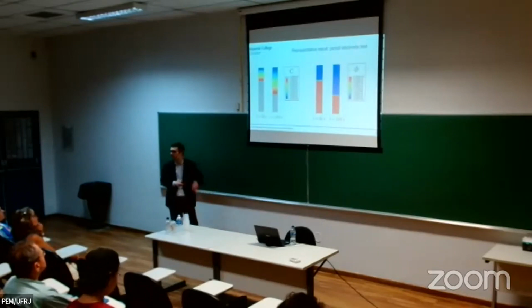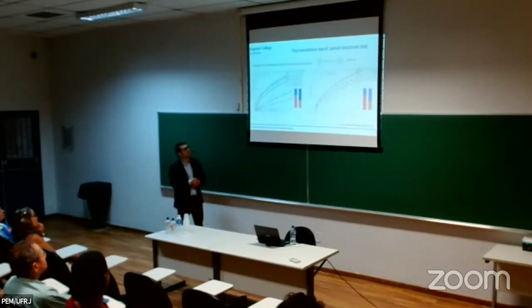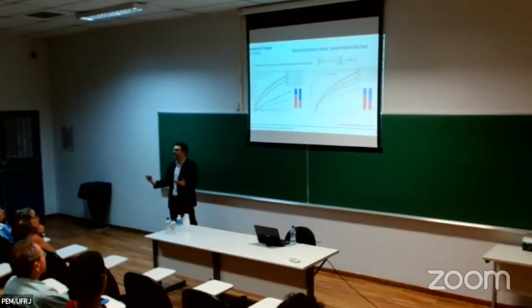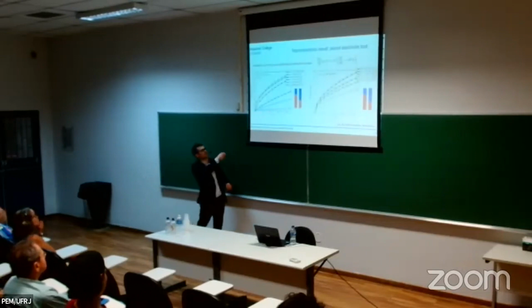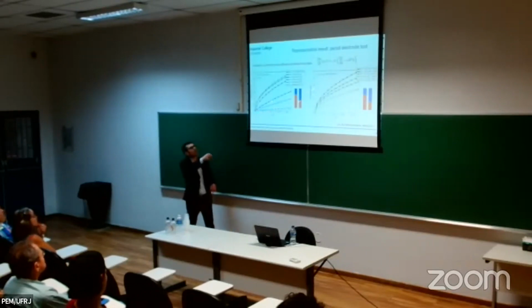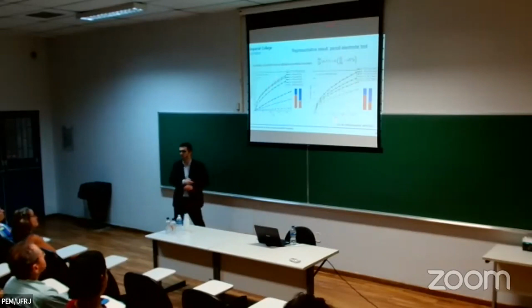You see effectively how the corrosion front evolves, and you see here the distribution of metal ions away from that corrosion front. And you can compare the model predictions with analytical solutions under diffusion control conditions. And we can also see that the model is naturally able to capture how we go from activation control corrosion, so this kind of linear behavior, to diffusion control corrosion, when corrosion rates are so high that diffusion is the limiting step. And in the diffusion control corrosion regime, of course, the results are dependent on the diffusion.